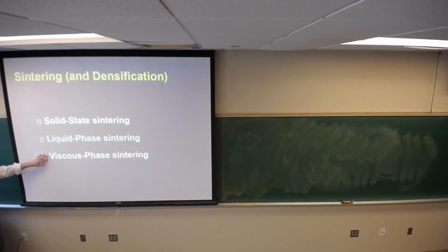Then you have viscous phase sintering, where you form a lot of liquid. Traditional ceramics are viscous phase sintered: porcelains, earthenwares, stoneware bodies. Our calculations and measurements show 55% liquid in the system at the densification point. So you're more than 50% liquid in the system. That's viscous phase sintering. If you're liquid phase sintering, you might be 3% liquid. And then you have to start dealing with the phase diagrams, which we can do.